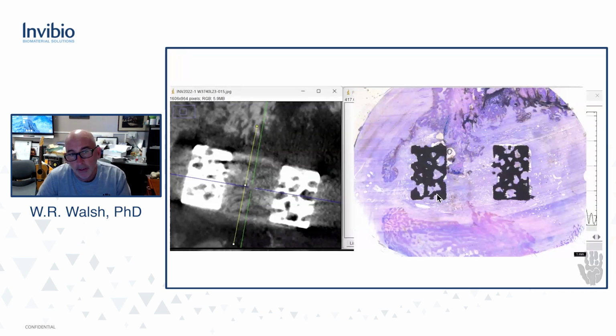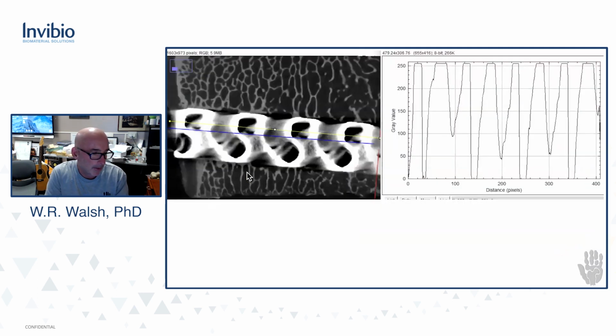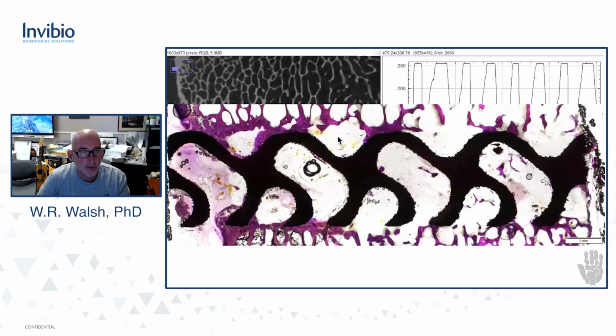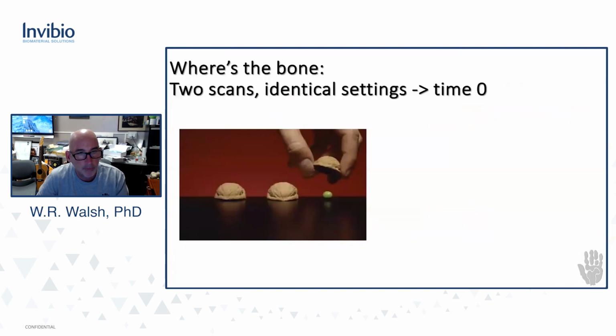And this is what the histology looked like of that case, but this is what the micro CT looks like. So we did some micro CTs of some other specimens. This is from the study we did with Ken and Cambry. This is a micro CT of a cancellous TPMS system or implant in bone. And again, you would wonder, is that bone or is it artifact? And it's artifact. The bone is primarily just gripping on the outside of it, not even coming into this structure here. So how an implant interacts in bone is very dependent on what bone you put it in as well.